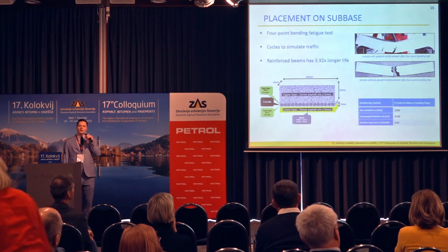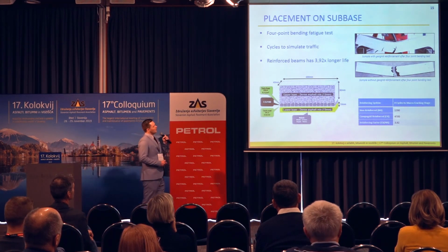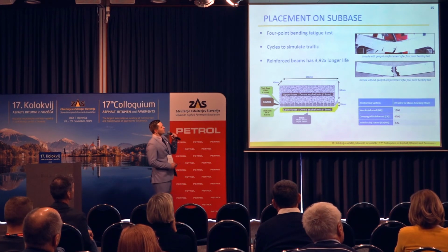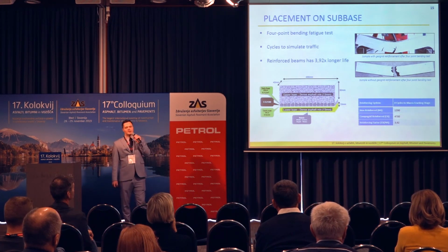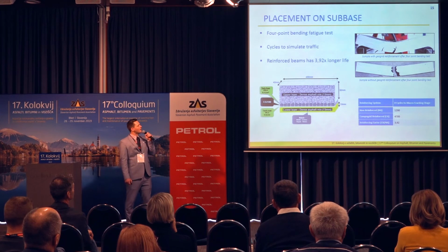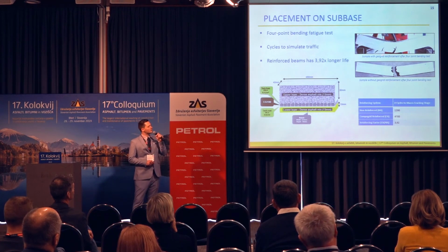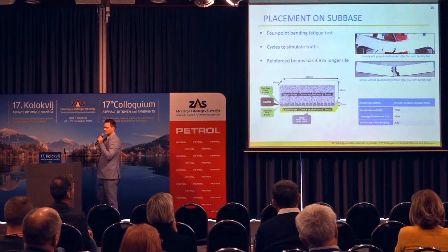And also this compo grid was tested in the lab on 4-point beam fatigue tests. So on the picture here, this is the beam with the reinforcement. And here you can see the beam without the reinforcement. This test is meant to simulate the cycles of what's happening in real traffic. And the cycles are calculated and compared. So in the case of this product, you can see that the reinforcement extends the life almost 4 times.